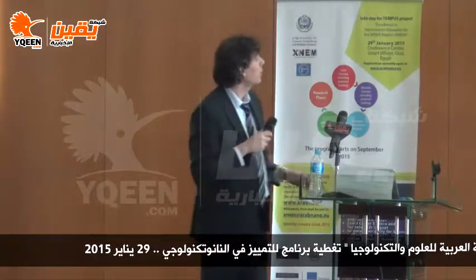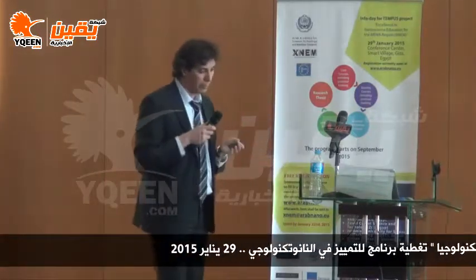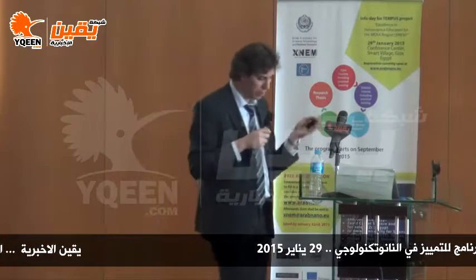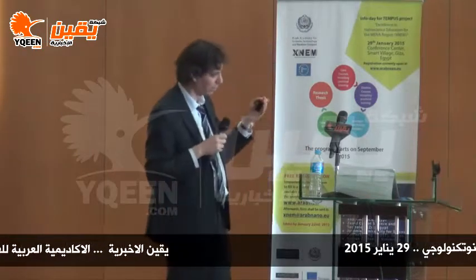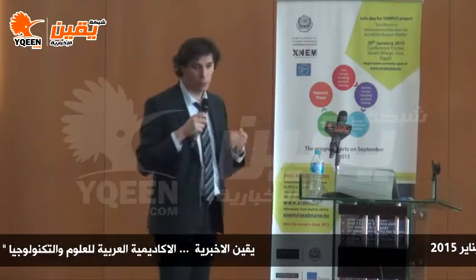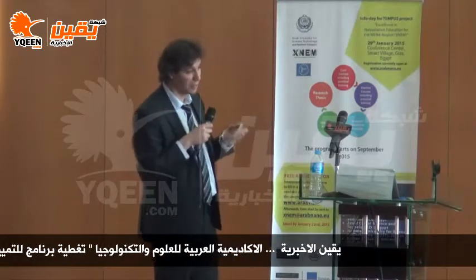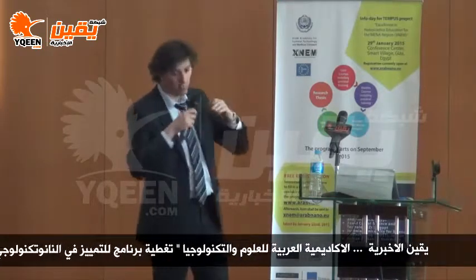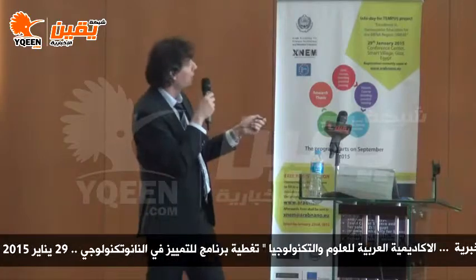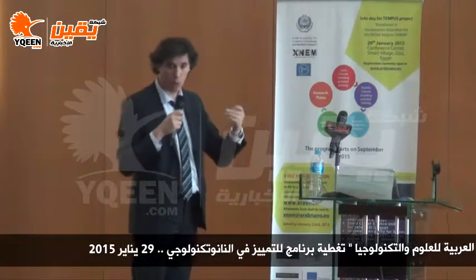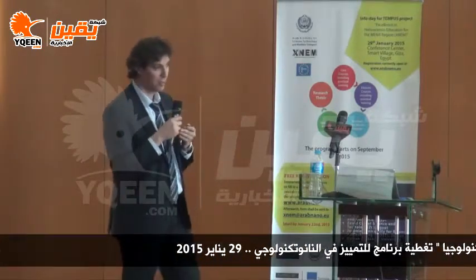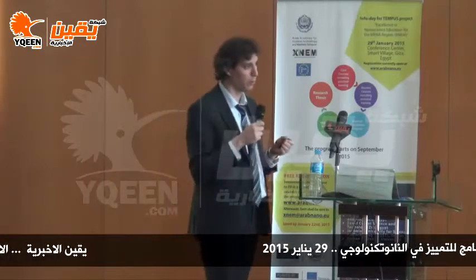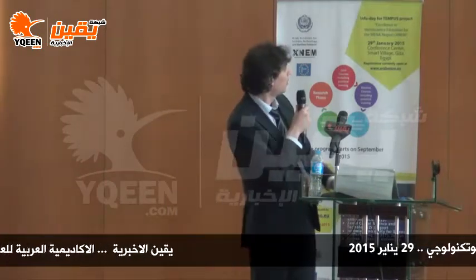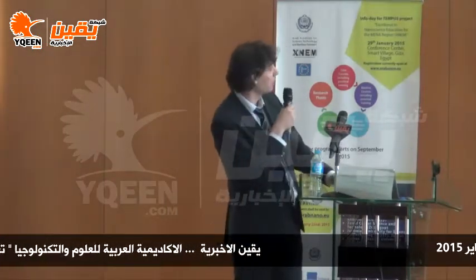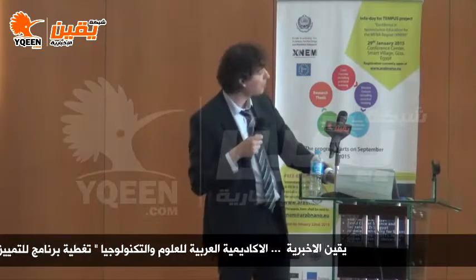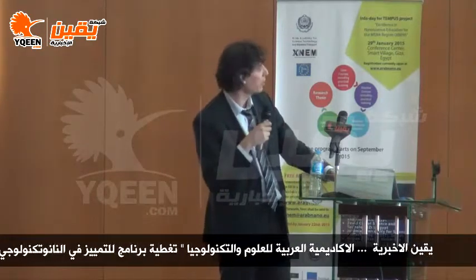And now we want to make UV photodetectors using such structures and p-type diamond. The problem is that when you grow diamond, you systematically end up with p-type on top of the surface, because the surface is hydrogenated. So you have a hole accumulation, and systematically your top surface is conductive. So how does this impact the performance of the photodetection?